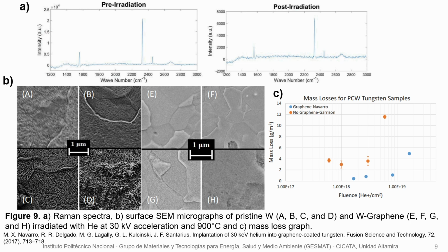We can see that even with the increase of the fluence, the surface damage is apparently reduced. Only some spots are seen with apparently more damage. The authors report that these spots with more damage in the sample with graphene coating are due to the transfer of the graphene, and the coverage of the surface was not homogeneous. Some spots have no graphene coating, and these are the most damaged ones.